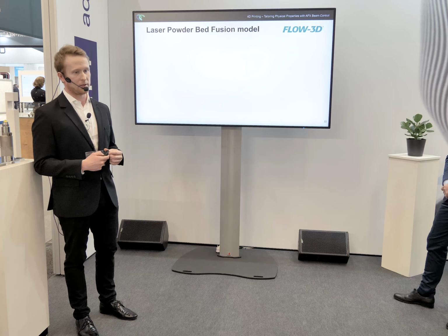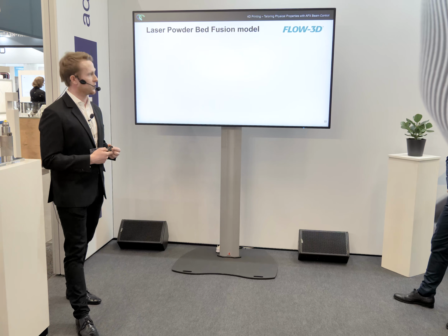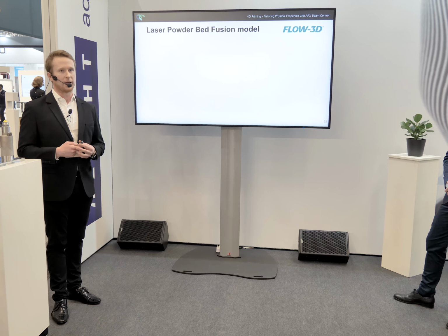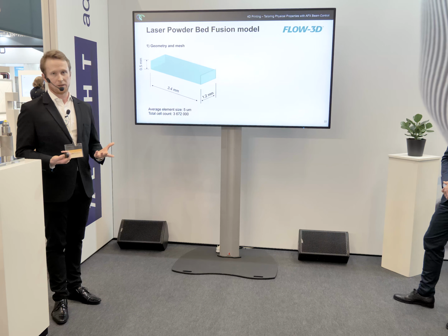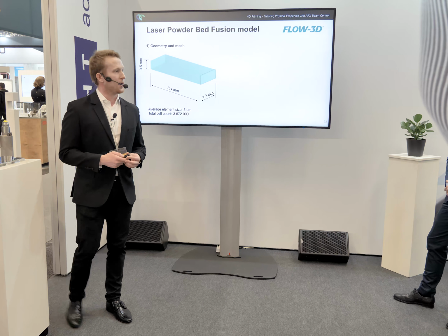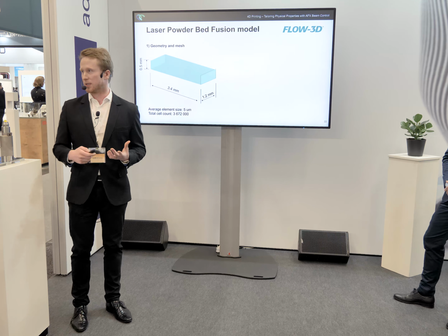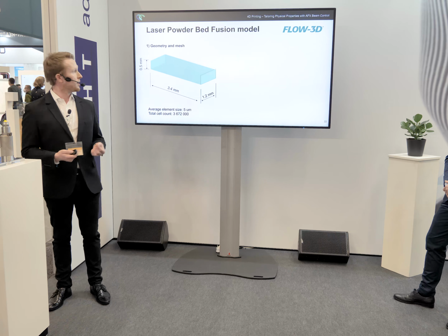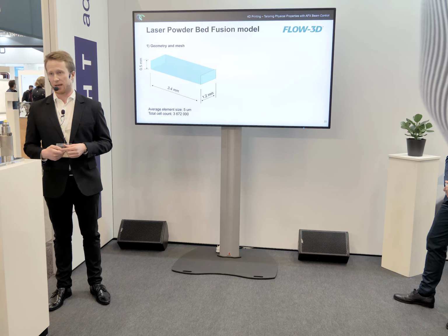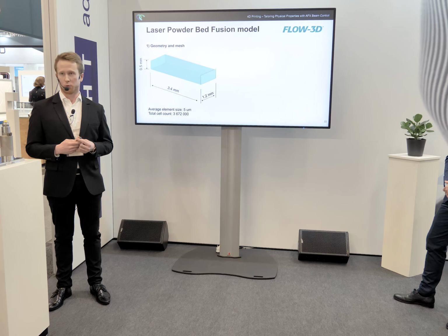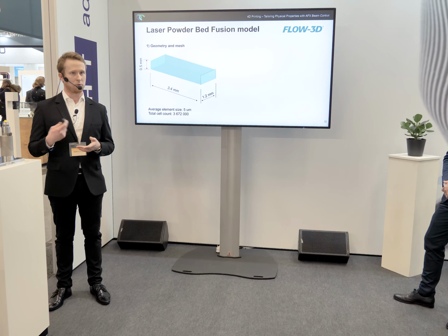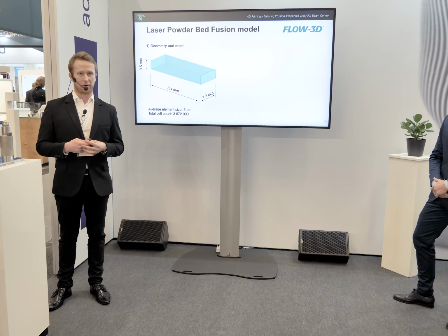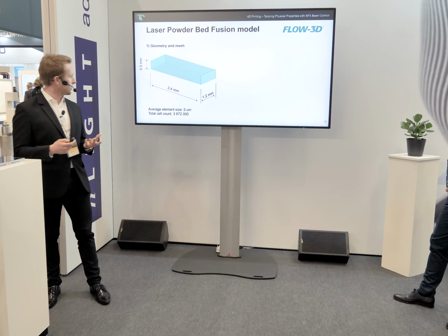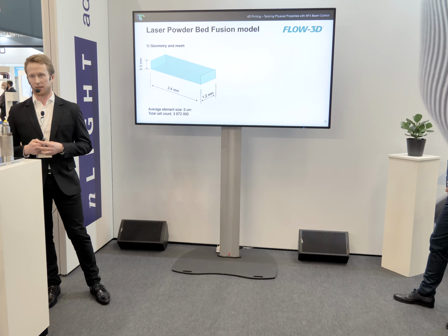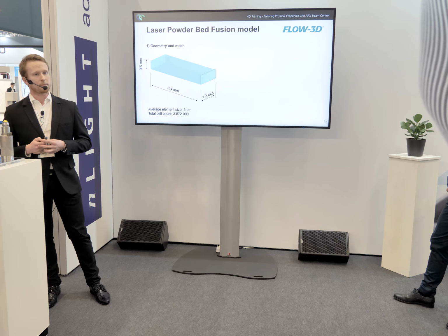So now a little bit about the model for this particular project. In any numerical simulation, we first define the geometry and the mesh. In this case, we have arrived with this quite simple rectangular geometry with an average cell size of 5 microns, which is basically the discretization with which we're going to solve the governing equations. And that yielded a total cell count of around 3.6 million cells.